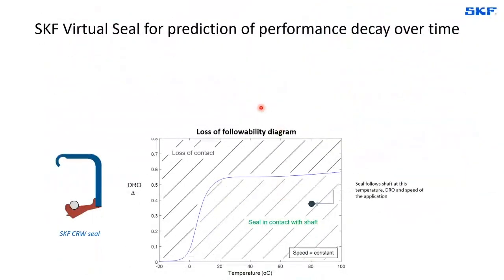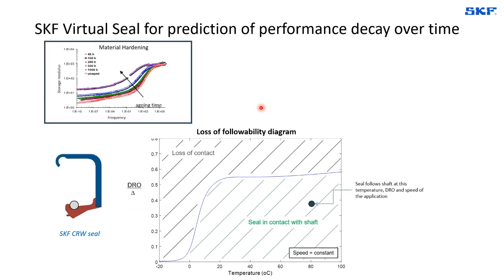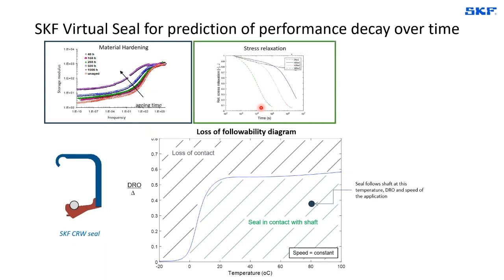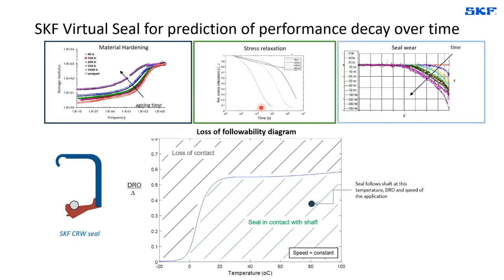If we can predict this performance for a fresh seal, we should be able, and this is what we do today, to understand the performance decay over time. In fact, as we understand that materials are hardening with the time of aging in application, but also that the stress relaxation is accelerated, or that the wear is somehow also present in application, we can then take into account through analytical models what will be the decay of the performance.